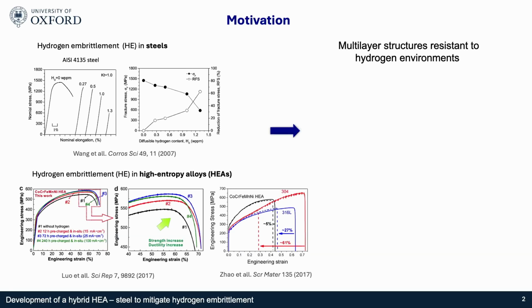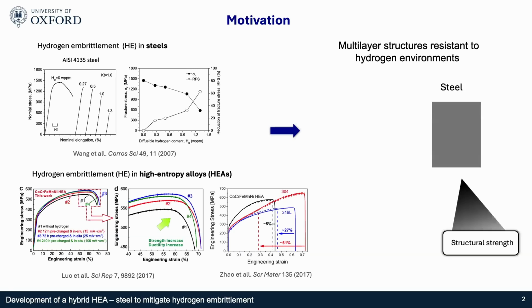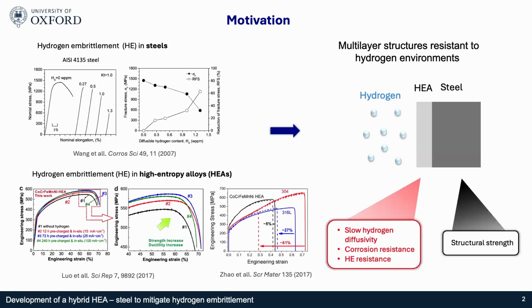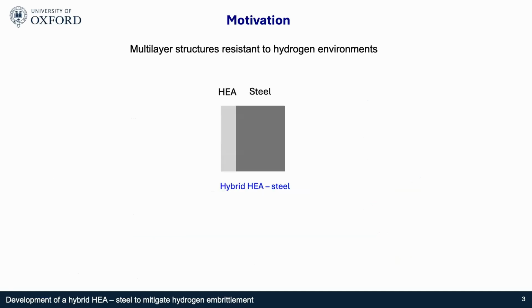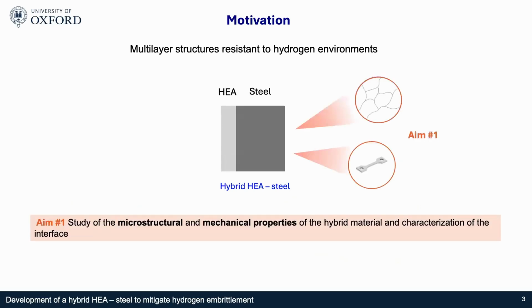So we propose a multi-layer structure that can be resistant to hydrogen environments. The idea is that the steel is going to be the core material, providing the structural strength. And the high entropy alloy with slow hydrogen diffusivity can delay the uptake of hydrogen to the steel and also provide good corrosion resistance and hydrogen embrittlement resistance. So the first aim of this work is to study the microstructure and mechanical properties of this combined or hybrid material, and also characterize the interface between the high entropy alloy and the steel.